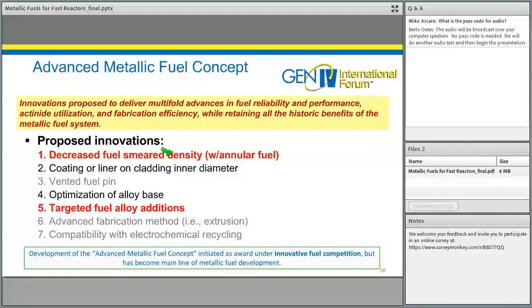One of the features was decreasing the fuel smear density. Metal fuel smear density was reduced to about 75%, and that gave the ability to get well over 10% burnup, but it doesn't allow you to go to ultra-high burnups that some people are now interested in. We thought for ultra-high burnup metallic fuel, we'd look at lowering the smear density even more. As you drive smear density lower, it becomes questionable as to whether you'd still want your metallic fuel slug to be a solid cylindrical slug. And so we wanted to look at an annular fuel form, specifically with the lower smear density as well.